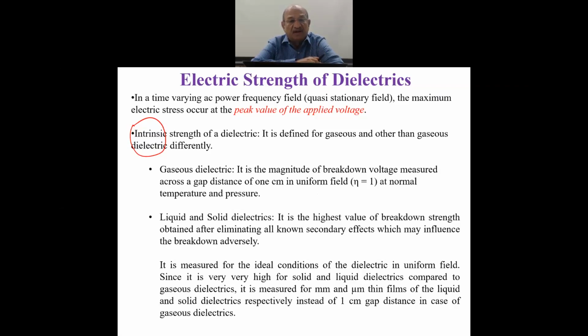There also we will learn later that the breakdown strength magnitude varies with the gap distance between the two electrodes. But for intrinsic strength, the value given is for a gap distance of 1 centimeter in uniform field, and that is something like 31 kV per centimeter in case of air. In today's highly used gas, SF6 gas, it works out to be something around 90 kV per centimeter, almost 3 times.